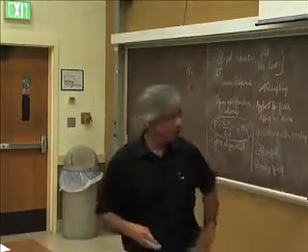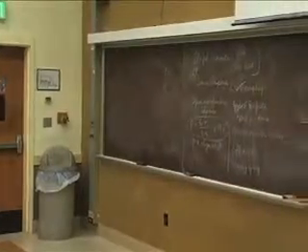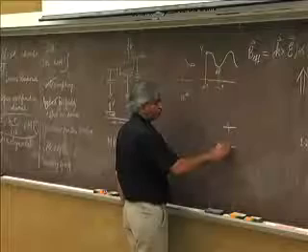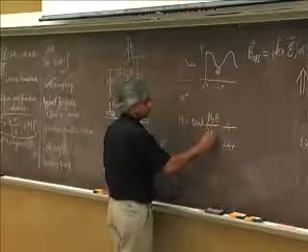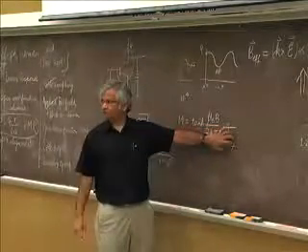The way you say it, the reason you have a magnet is people say that if you put a magnetic field, then of course up and down will separate, and you will have a lot more of one of them than the other. And you can show that the magnetization will be tanh(μB/2kT). The tanh comes from this ratio of exponentials.